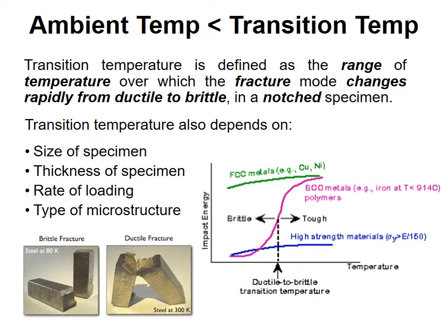As mentioned in the previous slide, let us now discuss further the ductile brittle transition temperature, which is also known as DBTT in short. DBTT is defined as the range of temperature over which the fracture mode of a metal when notched rapidly changes from that of ductile to brittle. It should be noted that only BCC metals have a ductile brittle transition temperature. The transition temperature therefore depends on the size and thickness of the specimen, the rate and magnitude of the loading, and last but not least, the type of microstructure, which is, yes, BCC metals.